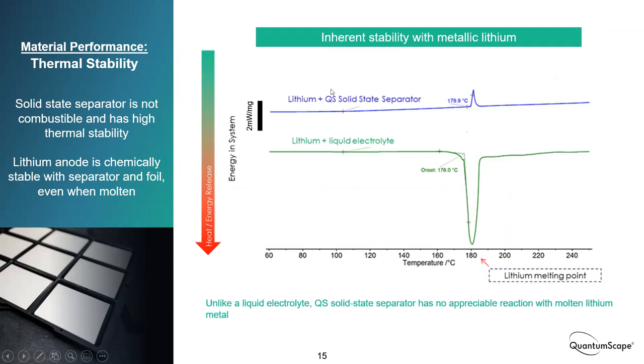By contrast, if you take Quantumscape's solid state separator and you do the exact same test with the same materials, the same amounts of materials, you heat this system up, instead of seeing heat released due to reaction, you actually see a little bit of heat absorbed. This is the melting of lithium. It happens at about 180 degrees Celsius, and then nothing else happens. So there's no reaction here. So it's a very, very stable material. And fundamentally, I think that's the key to improving stability of the whole system.